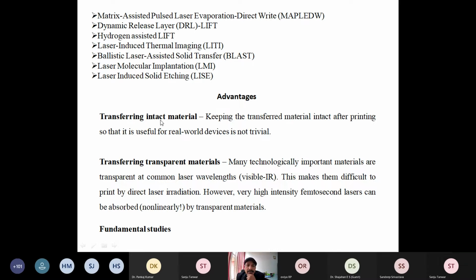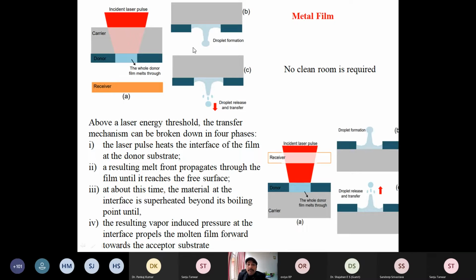There are several advantages are there. Because intact circuit or design you can directly implant on the surface, and some of the material where the laser cannot use to create a structure, that means the substrate is not going to absorb the laser radiation, then there we can use this technique. In case of metal films, this is we have very specific structures. For example, here the metal film is there, and when the laser pass through, so this become heat up, so it have take the shape of drop, and this drop you can catch on the substrate. In case of backward transfer, this is in reverse, because substrate is positioned here and the metal coating is here. So in reverse of that, the forward direction deposition, we have a reverse backward direction depositions as well.